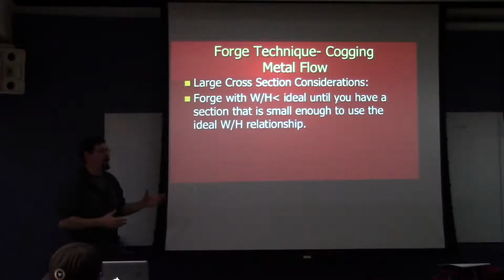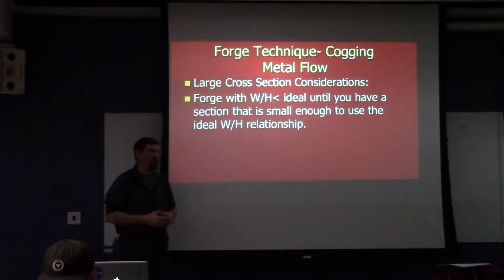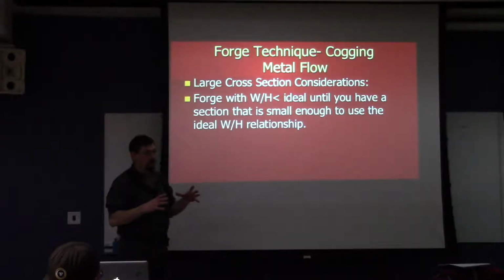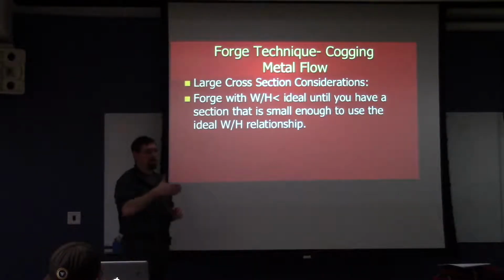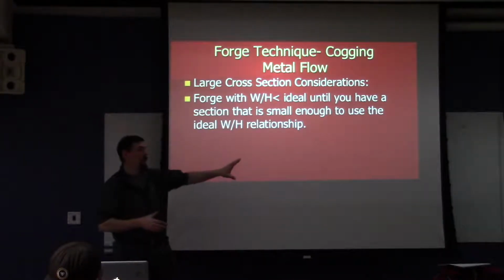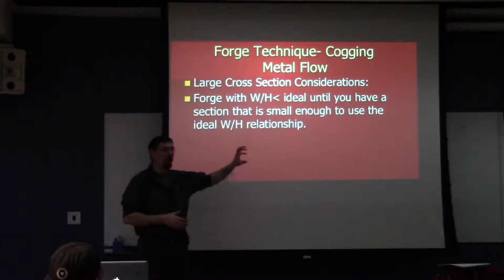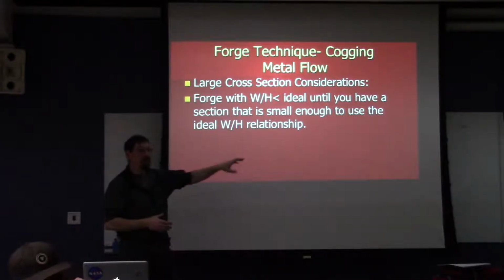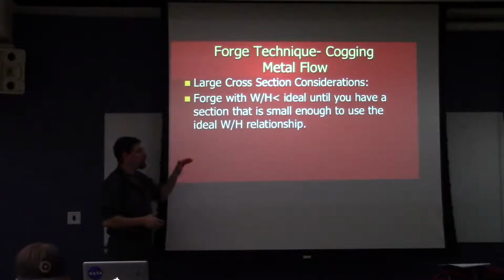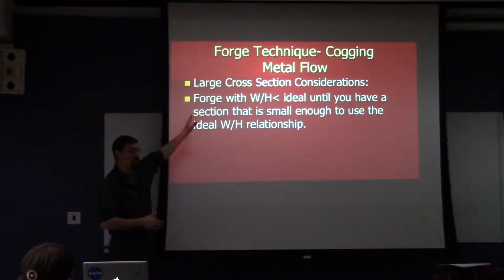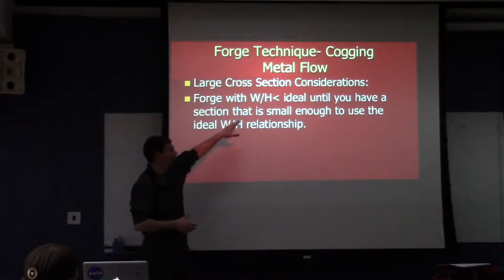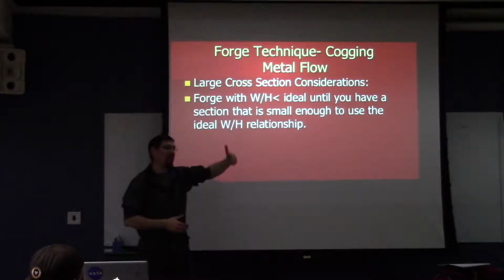What can happen is that the work they do in the first heat gets them to a size that's so small that in the next heat or two, they don't have enough work left to do in the part where they can get that 3-to-1 effective reduction. So it's really important that they recognize that this condition exists, that they're going to take this step on purpose, but then they're going to stop.